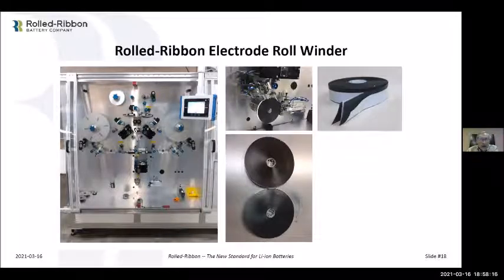What happens is we take those feedstock rolls that we got from slitting and load them up here, an anode and a cathode over here, on the machine. We put a winding hub on the arbor. The arbor actually sits right down here, so this is a close-in shot looking at it. We put a hub on there, and this builds a web of rolled ribbon in the Z fold. It Z folds the separator and tucks the two electrodes between, and you can see that here. Here's the anode, there's the cathode, here's the Z fold separator. It keeps the two electrodes separated from each other.